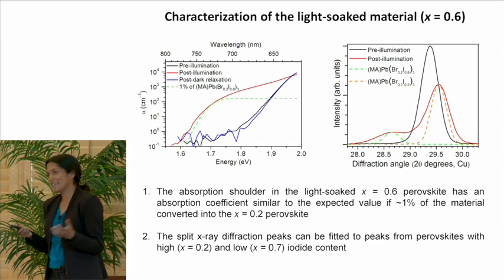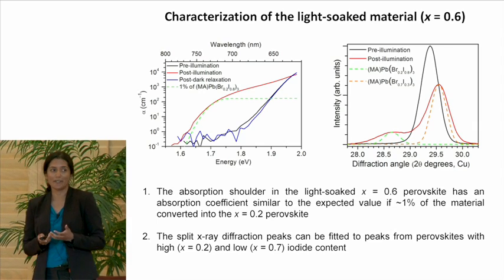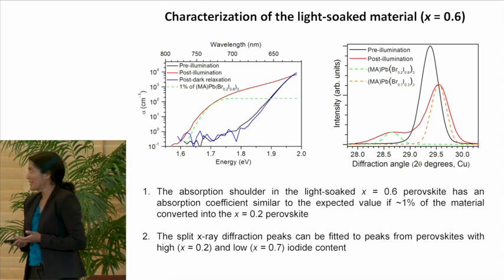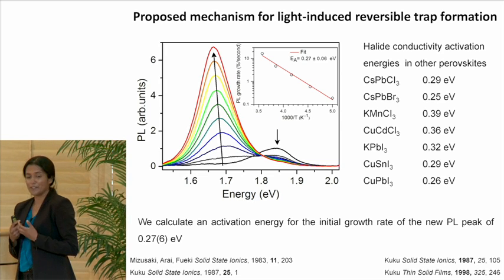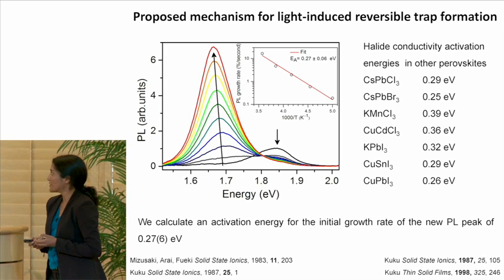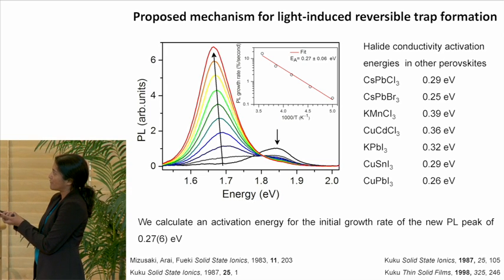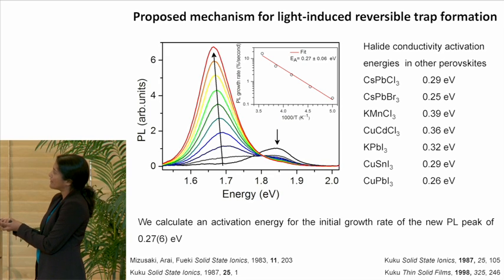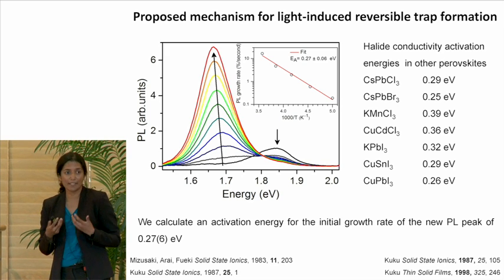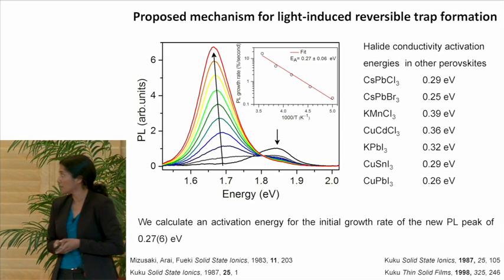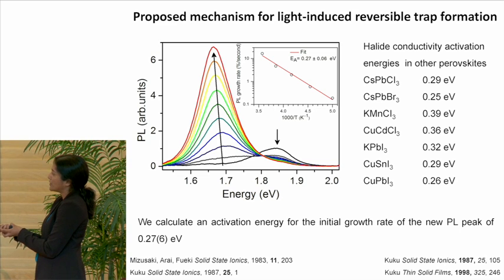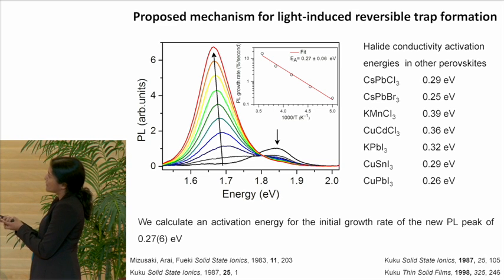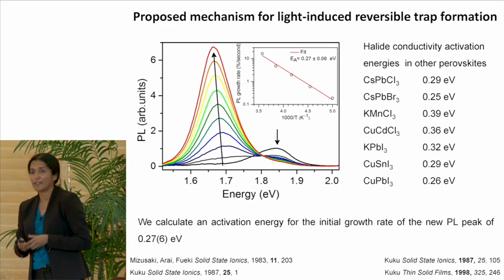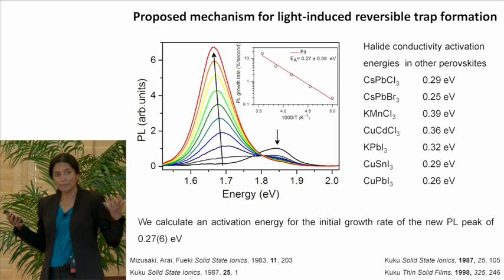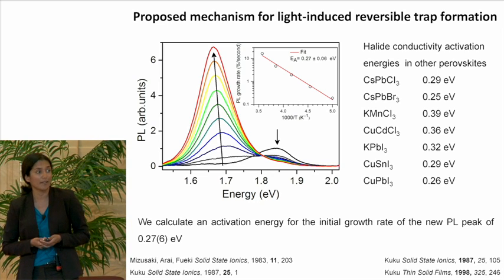So halide segregation implies halide motion under illumination. And we know that this is a thermally activated process, because at different temperatures, we see different rates of this photoluminescence band growing in. And we can calculate an activation energy for this process. We get a number of about 0.27 eV. And this number fits very well with activation energies that have been attributed to halide migration in other metal halide perovskites.